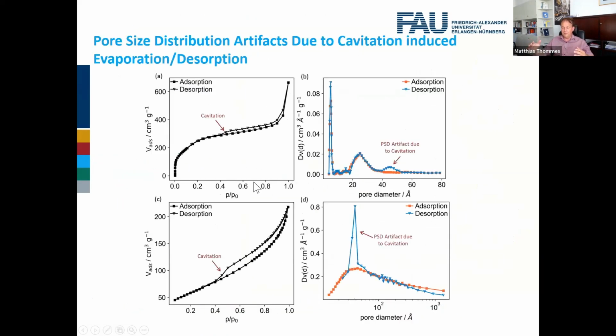So this is something you then also know. If you have cavitation happening, you know that pores are connected in an unfavorable way. You know that you do not have large pores leading to small pores, as you would like for advanced transport phenomena, but the other way around. Here is a more drastic example. This is a really classical alumina catalyst support.